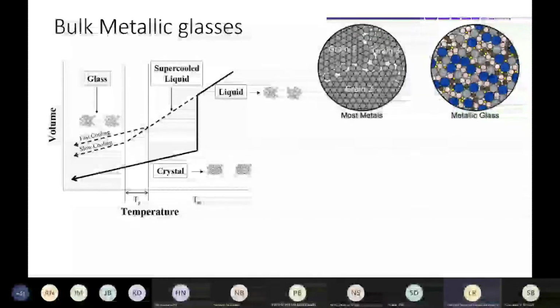In contrast, in metallic glasses, you have several components. Here in this case, you can see 4 elements; 4 different kinds of spheres have been used. And because of this, the structure is very random. Since the structure is very random, you cannot really delineate a space where there is a fixed organization of atoms, or a fixed order of atoms. So these are highly disordered atoms sitting in a pool. And this is a solid. Don't think this is a liquid. This is still a solid.